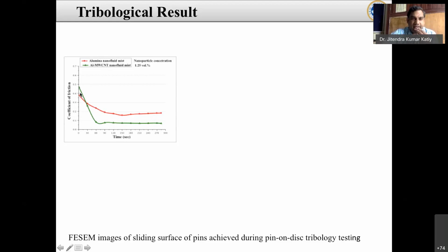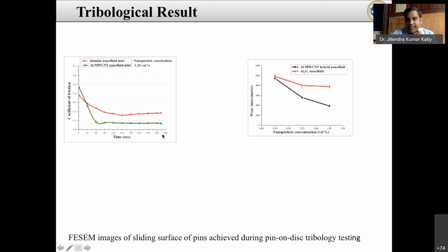So initially, why does the hybrid cutting fluid show the higher coefficient of friction? Because when two particles are there, shearing takes place and they can exert more pressure over the surface. After that, what happens? The three-body phenomenon occurs, and the particles can easily roll. Initially your pin slides over the particle, so the coefficient of friction is high. But after sliding, it starts rolling, and rolling friction is always lesser than sliding friction. Because of that, the friction goes down at the interface with respect to time, and wear is also less in the case of the hybrid nano cutting fluid.